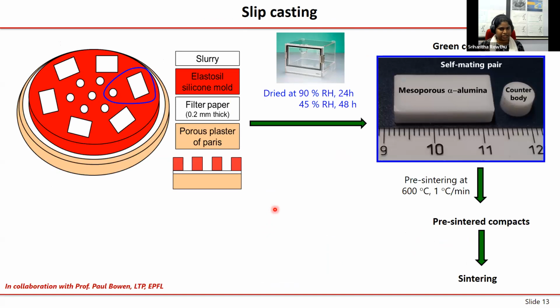Now, this slurry is nicely de-agglomerated and we are going to cast it into a mold. For that, we have to do some assembly. Firstly, we will prepare this yellow colored base. It's actually plaster of Paris, which is nothing but calcium sulfate 0.5 water, CaSO4·0.5H2O. On top of it, we are going to place a filter paper, and on top of that, some sort of silicone mold.